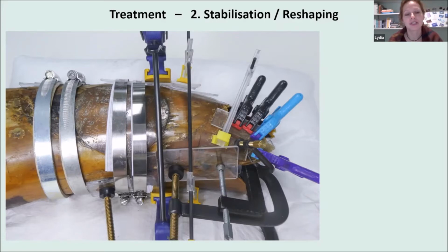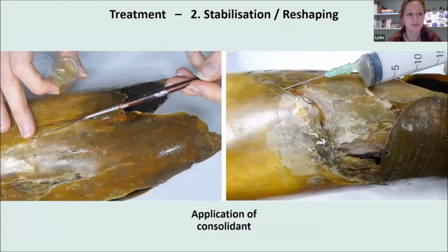Before I could tackle the distortions and large cracks in the horn, I had to turn the adjacent laminating layers back into a compact sheet of horn material. To consolidate these layers, I decided to use protein glue. This glue is water-based and was well matched to the intertwined reshaping process, which required ongoing humidification. A water-based adhesive can react, adapt to slightly changed shapes, and harden out again in the new position. I chose bone glue as it will be strong enough to recreate a rigid and stable horn sheet and withstand the pressure I will need to apply during the reshaping process.